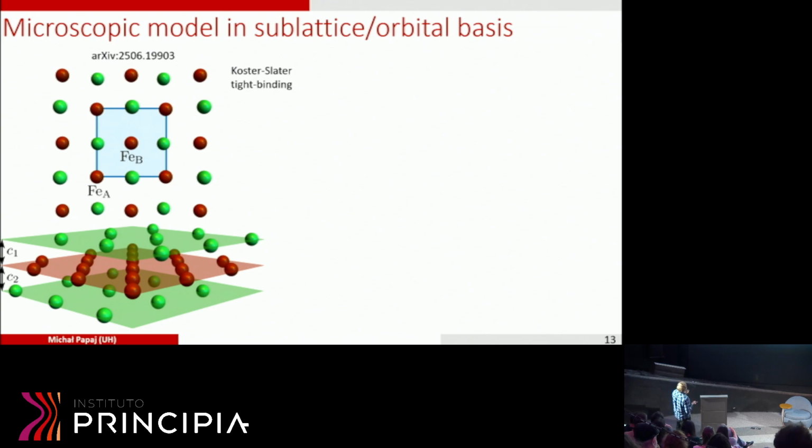One thing that establishes this equivalence between A and B sublattices is the glide mirror symmetry. So we can shift and flip our lattice and get the same thing as before. So it seems like this glide symmetry is broken in this case. If we are at the surface, then it's certainly the case because, obviously, above the top selenium layer we have vacuum, and below the bottom selenium layer we have the crystal. So this certainly breaks the glide mirror symmetry.